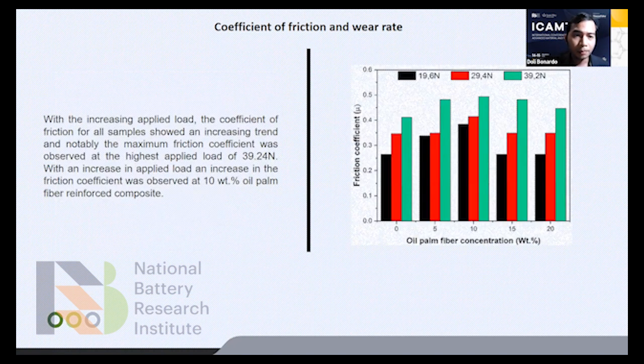And with the increasing of applied load, the coefficient of friction for all samples showed an increasing trend, and notably the maximum friction coefficient was observed at the highest applied load of 39.24 Newton, with an increase in the applied load and an increase in the friction coefficient observed at 10% weight percent of fiber reinforced composite.